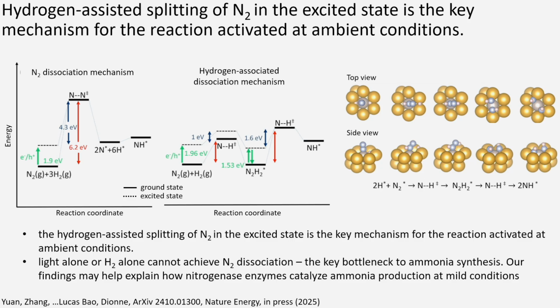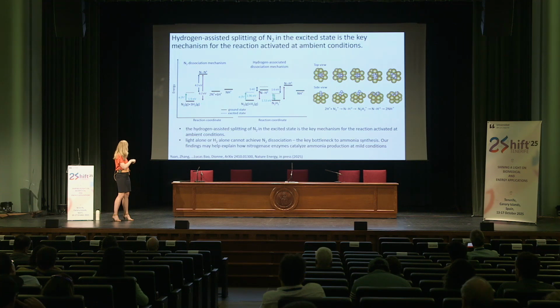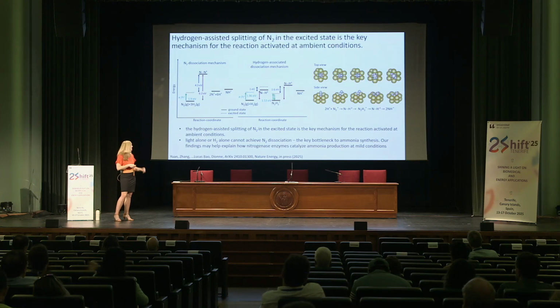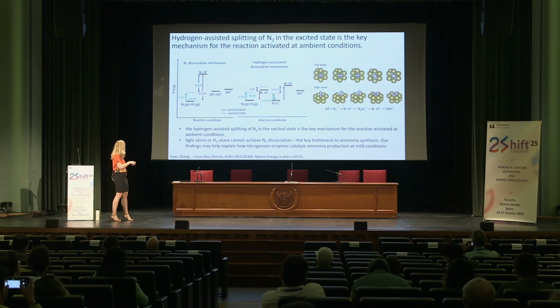First of all, we've changed the intermediate energy levels, but the energetic barrier to go from N2 plus H2 to this N dissociated bond is still quite substantial. It goes from 6.2 electron volts to 4.3 electron volts when you're in the excited state. So with visible frequency light, we're still not going to be able to overcome that activation barrier. But now if we look at this hydrogen-assisted splitting of nitrogen, in the excited state, we bring that energetic barrier from what used to be about 2 electron volts down to 1 electron volt.